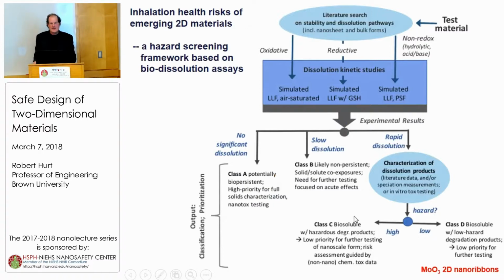So I think we would call those class D materials, not a high priority for further detailed study. Then there's materials that are biosoluble, but they produce toxic byproducts. And we didn't have one of those in our example set, but an example might be nanocopper. It oxidizes pretty rapidly, gives off copper ions, and is quite toxic in the lung through the redox activity of the copper ion itself. It has to be treated differently, but I think our attention is better paid to the chemical aspect of the toxicity rather than the particle-specific aspect. And then we have materials that are in between that dissolve slowly, and I think molybdenum disulfide is one of those. And we finally have materials that show no dissolution.